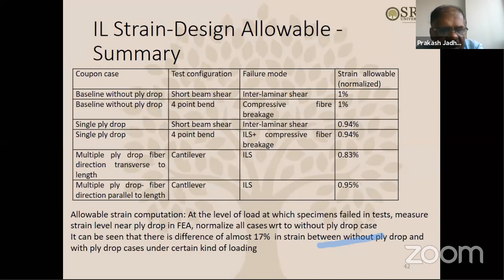Similarly, for multiple ply drops also, we can see that under the cantilever condition and ILS kind of failure, strain allowable could be like 0.83 and 0.95. Means if you compare with the baseline specimen, the difference is almost like 17%. 1% to 0.83 is almost 17%. So in multiple ply drop specimens, the specimens are going to fail because of presence of multiple ply drops by even as high as 17% earlier in terms of failure strain. Okay. So this is what it shows.